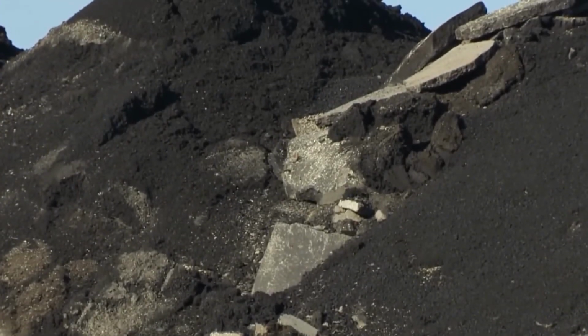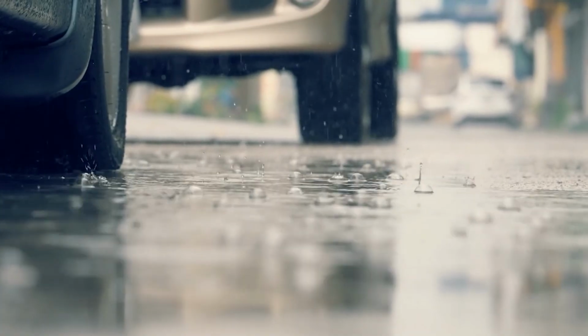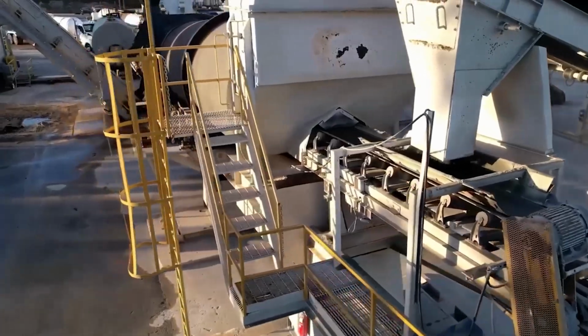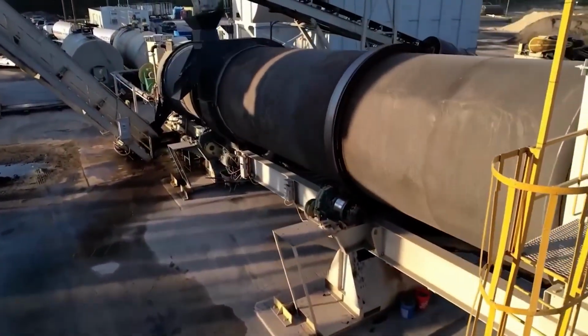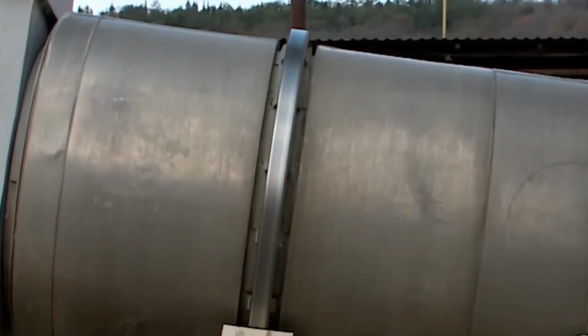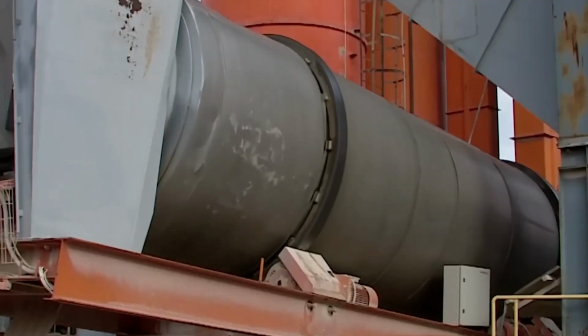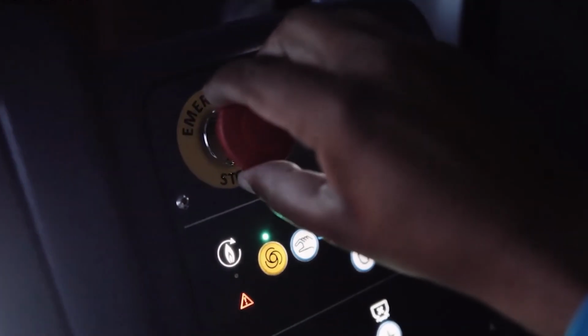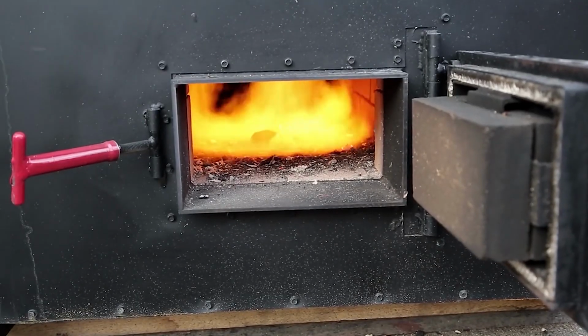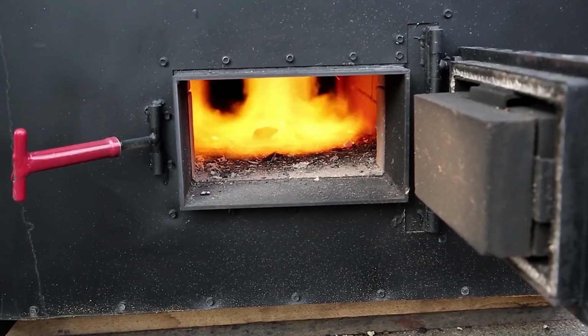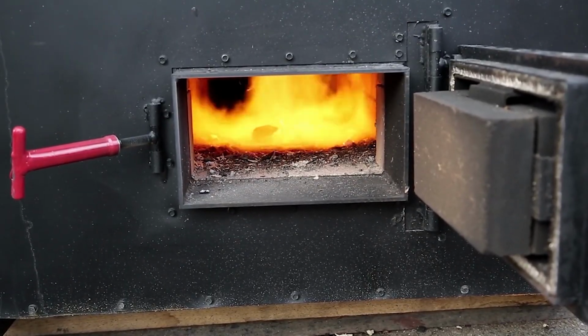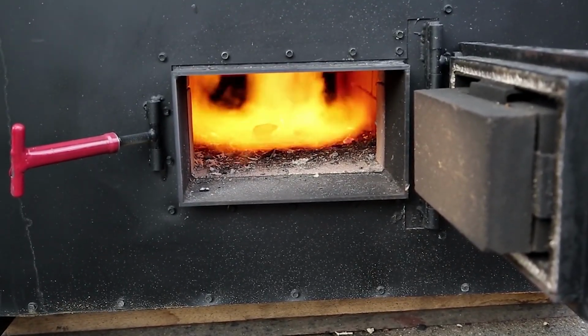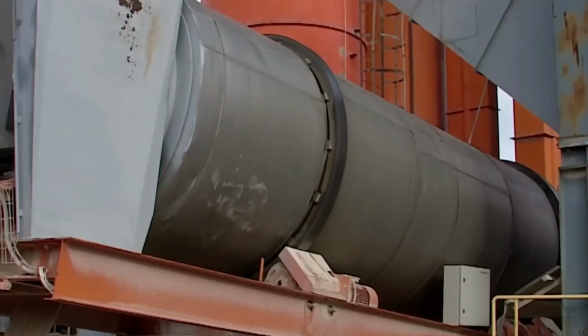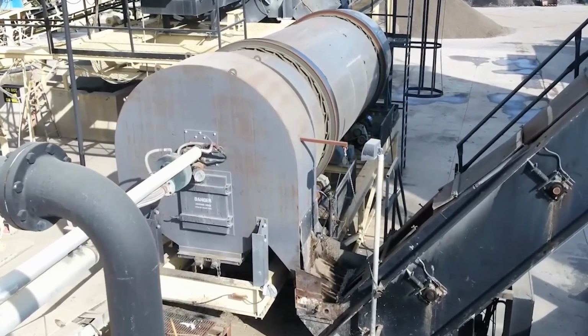RAP piles are stored outdoors. They soak up rain. To heat wet rock, you first have to pay the energy penalty of the latent heat of vaporization. You must boil off the water before the rock temperature can rise. Moisture load, industry limit often approximately 5%. If moisture content spikes above critical levels, the burner must work exponentially harder. If the dryer cannot vent the steam fast enough, it overwhelms the filtration system, forcing a plant shutdown.